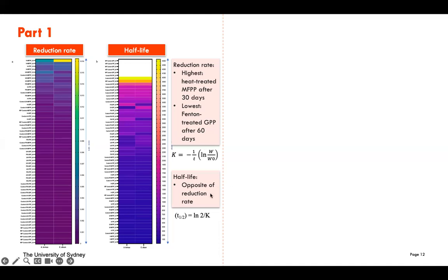So then the half-life will show the opposite of the reduction rate. So you can see that the half-life, of course, the highest will be the control, because this is almost infinity actually. None of the polymer were degraded for the controls, but it is highly degraded, or the half-life is much, much lower for those polymers that are pre-treated by using heat and also UV.